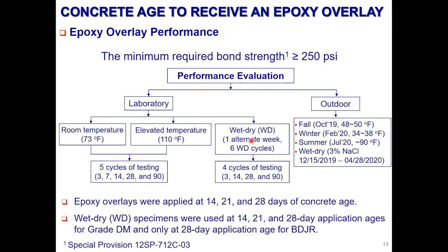We subject the overlays to wet and dry cycles. In this case, we use 3% sodium chloride as the medium for wetting the surface. And also we place the specimens outdoor and conduct the testing during fall, winter, and summer.